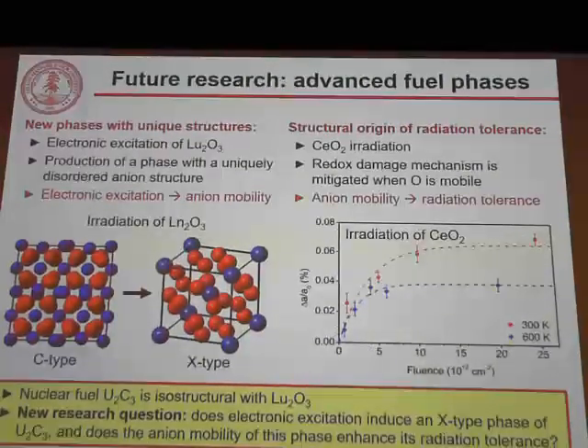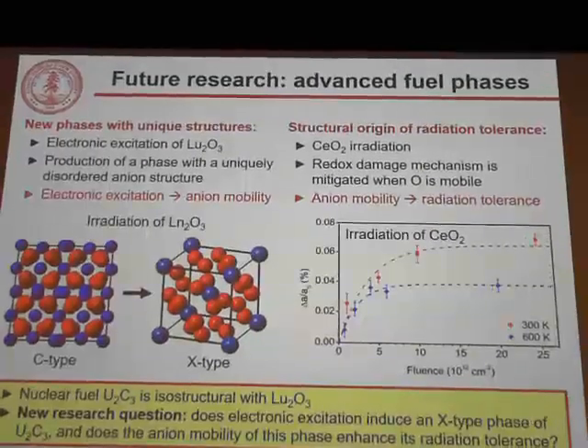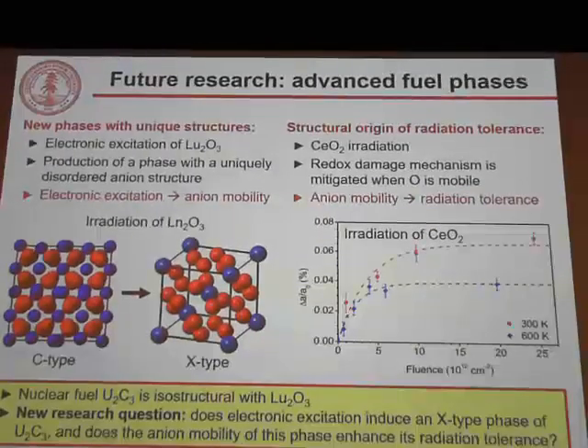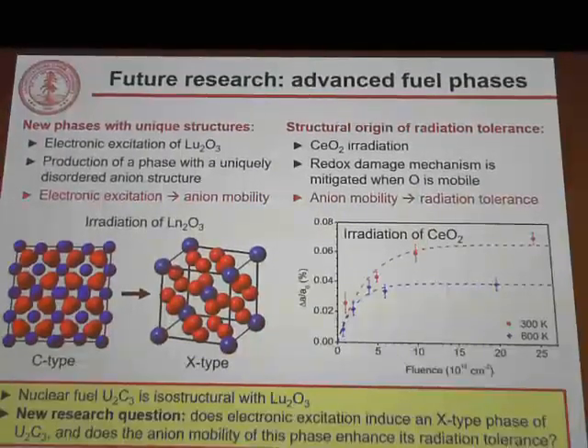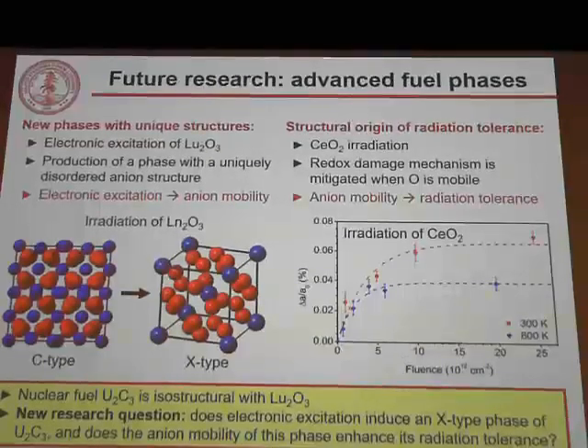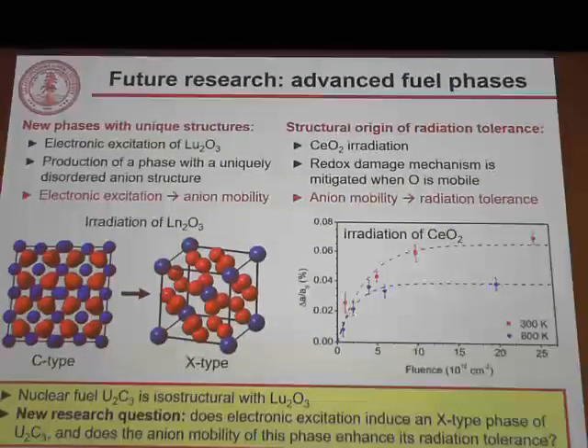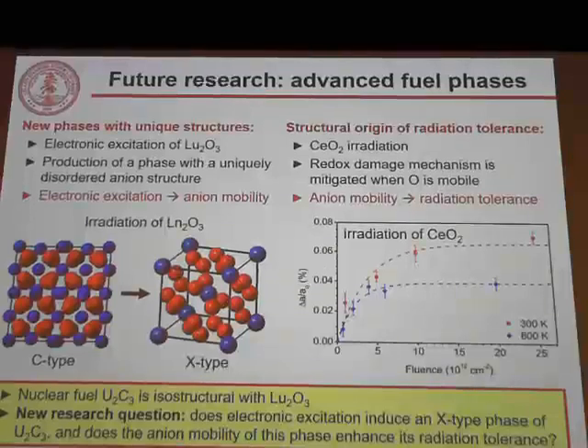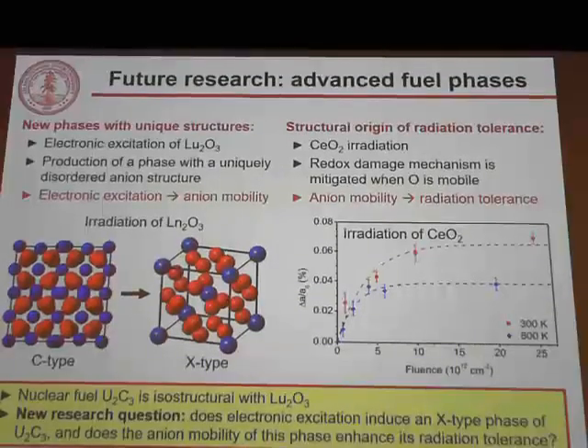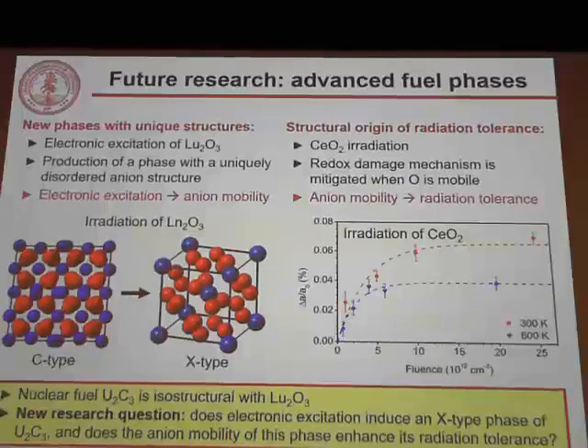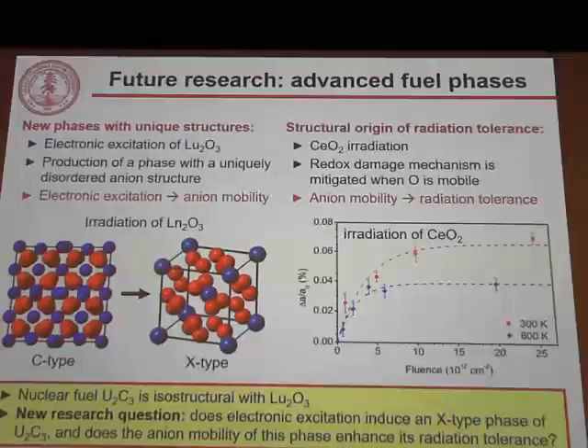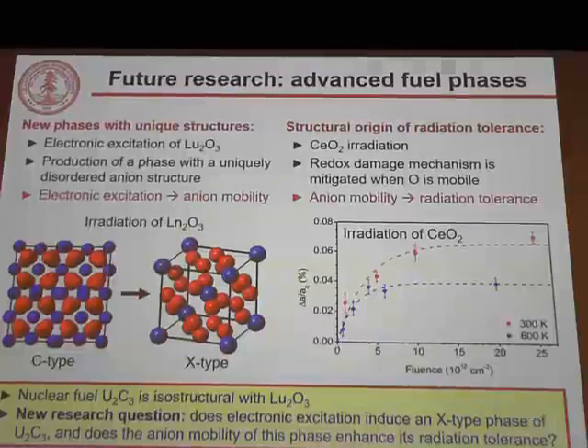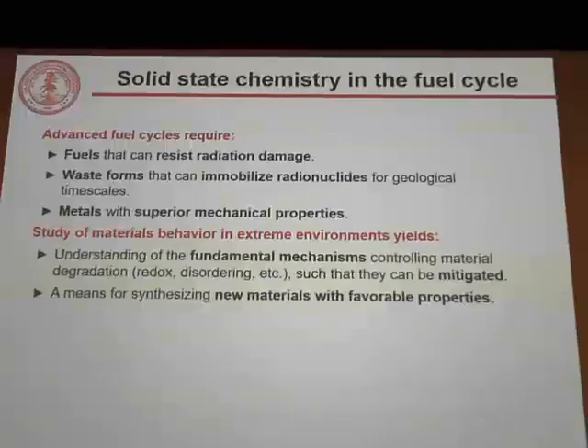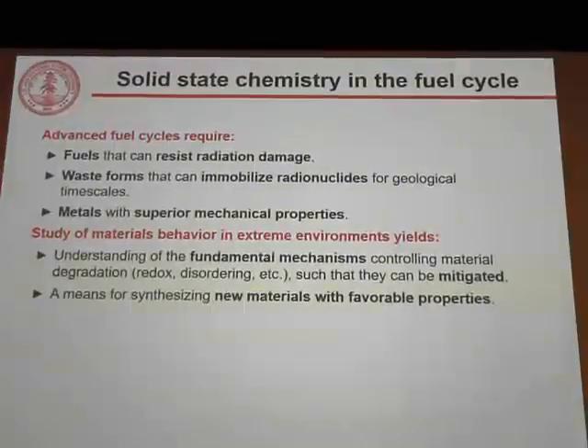This is especially interesting because a possible nuclear fuel material, uranium carbide, is isostructural with lutetium sesquioxide. So we might ask, does it undergo this same transformation to this unique X-type phase if we process it with these extreme processing conditions? And if that does happen, does the anion mobility associated with this phase yield better radiation tolerance?